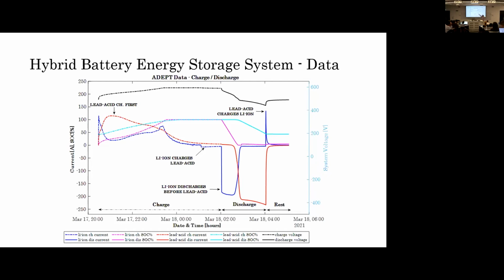So as you start discharging, there is an equal share, then lead acid picks up the peaks. And when you stop discharging, that's another thing we looked at. There is a little bit of a spike at the end of it. Basically, what happens is the other way around. So lead acid now, between the strings, you could say that's loss of efficiency, that's not good, and you're probably right. In this case, though,